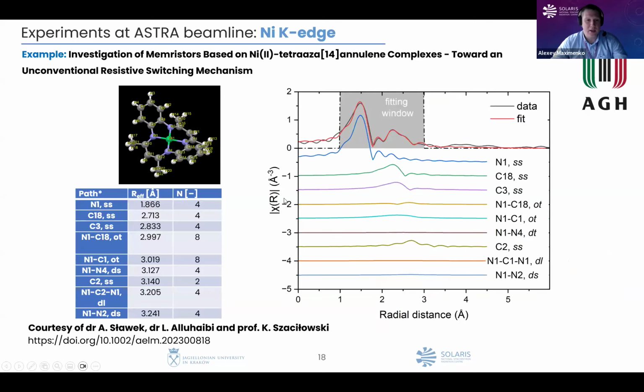Also, later on, using the analysis of XAS spectra, we managed to unravel the structure of such nickel-containing complexes. We can unravel the distances between the nickel atom and the atoms in the first, second, and third coordination shell, and also the number of these atoms in each of the shells.